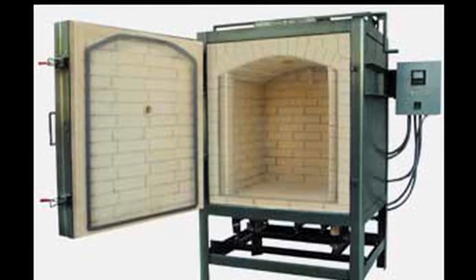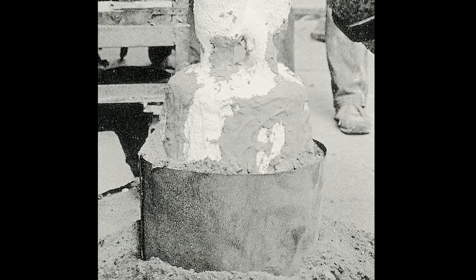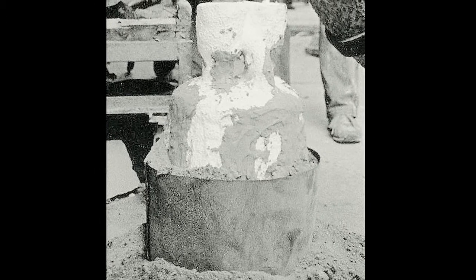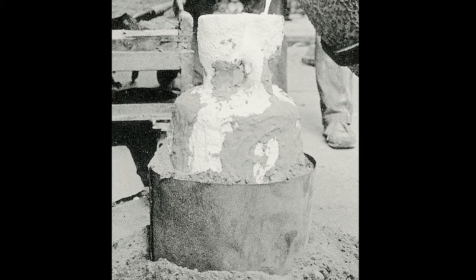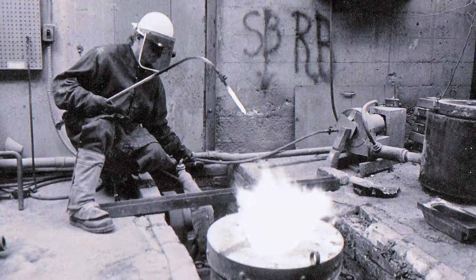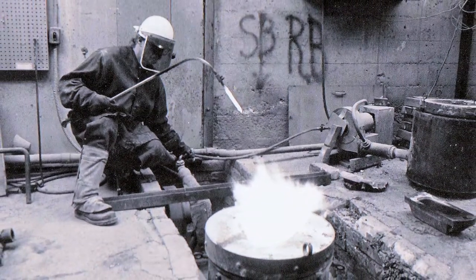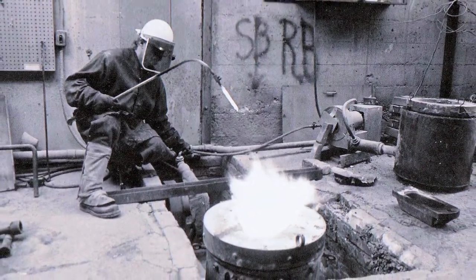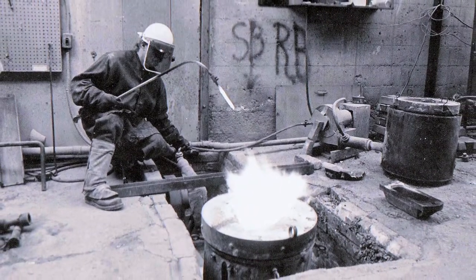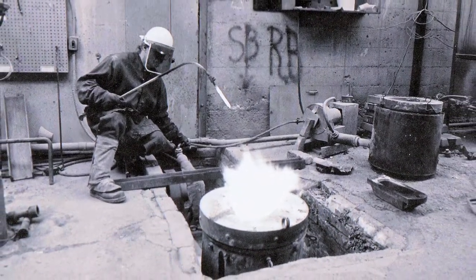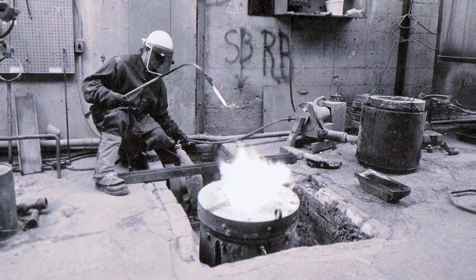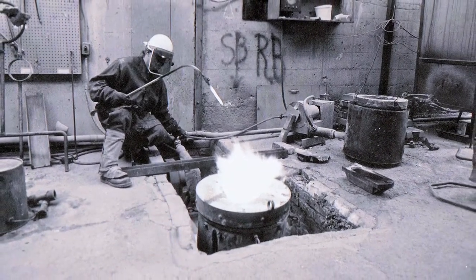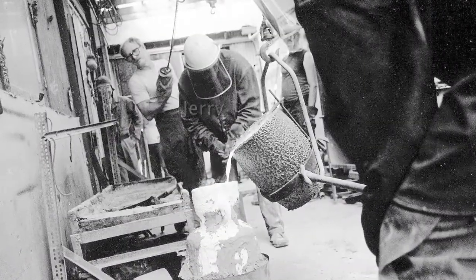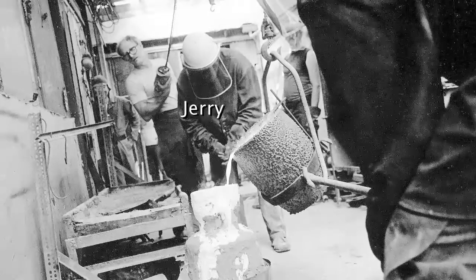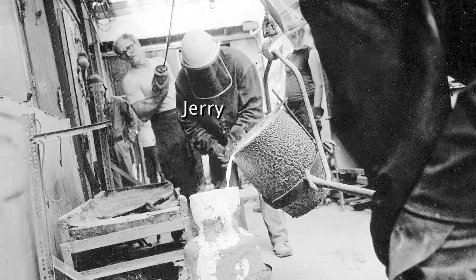After we checked it for leaks, we set the ceramic shell in a metal container and packed sand around it to keep it from collapsing. Now comes the fun part. Though the melting point of bronze is around 1700 degrees, for this project we needed to raise it to 2200 Fahrenheit to ensure that the metal remained molten until the entire mold was filled. We melted 200 pounds of bronze and poured 180 pounds into the mold.